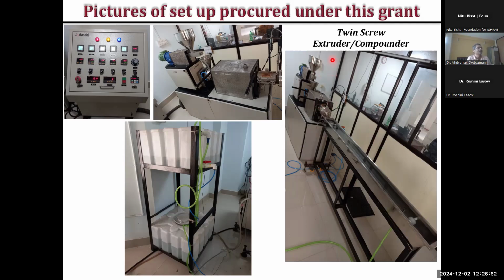So what we do, we put in the pellets. Pellets are small granules. Here we use polylactic acid, PLA, with supercritical carbon dioxide, SCO2, that we mixed here. And then we set the temperatures. Here is the typical barrel system. In this, there are twin screws meshing with each other. Material is fed here. There are 3 heating zones. The most critical thing in all these manufacturing systems is what speed of screw you set and what temperature you set to get an appropriate foaming element. And this is where, in experimental investigation, it takes quite some time, around 6 months, to optimize, to look around, to revisit and come back with that optimum structure.